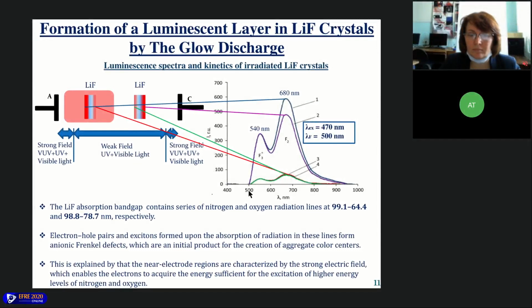After obtaining the result, we can conclude that the color center formation is not provided by an electron mechanism, electron bombardment. It is provided by a photon mechanism. Electron-hole pairs and excitons formed by the absorption of radiation in this line form anion Frenkel defects, which are the initial product for the creation of aggregate color centers. So let's go to the conclusion.